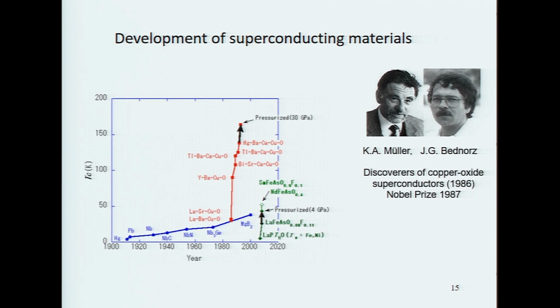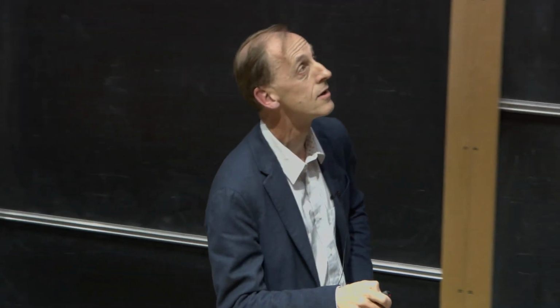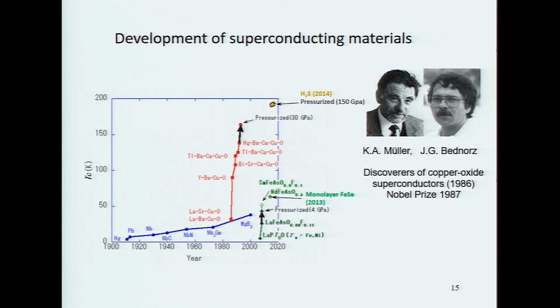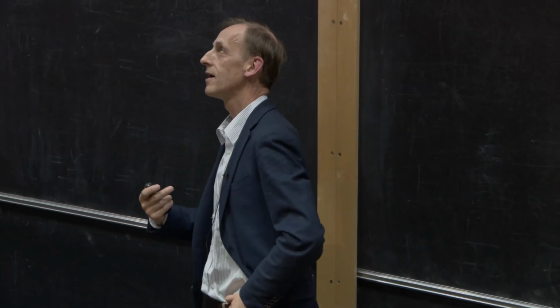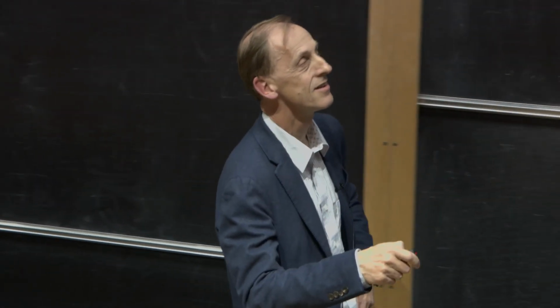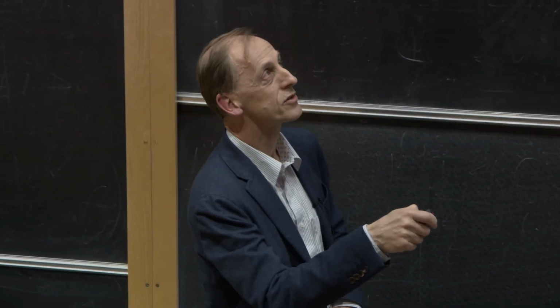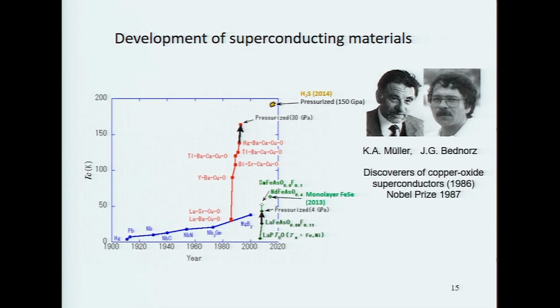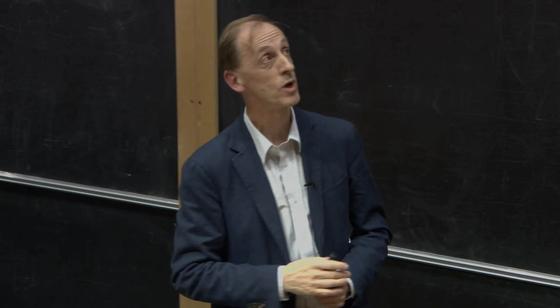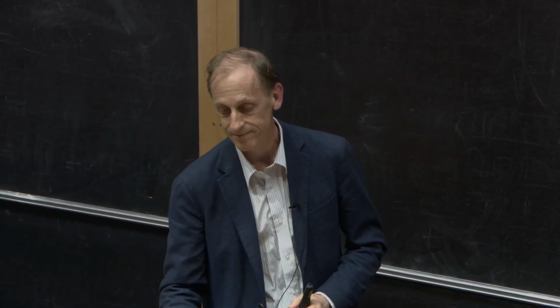And even 3 years ago, this field is moving on, a group in Germany discovered, and you won't believe this, a superconductor based on hydrogen sulfide, stink bomb, where if you pressurized it to unimaginably high pressures, these are sort of geological pressures, 150 gigapascals, that's more than a million atmospheric pressures, I think. Then what they found was they got a superconducting material which worked at just below 200 Kelvin. So that's a world record for the highest temperature that we have at the moment.